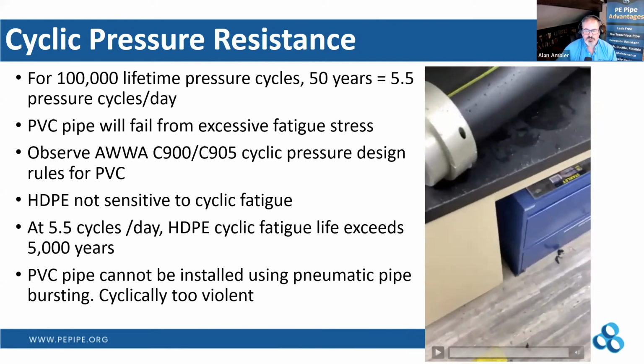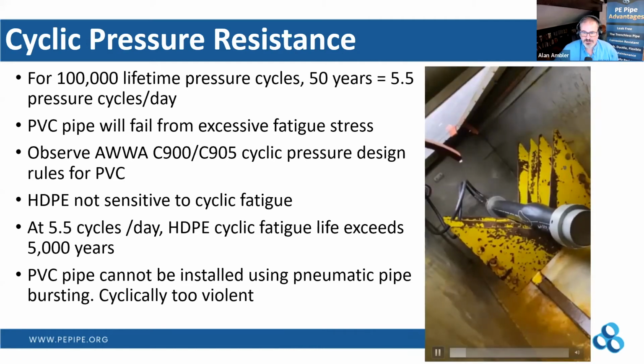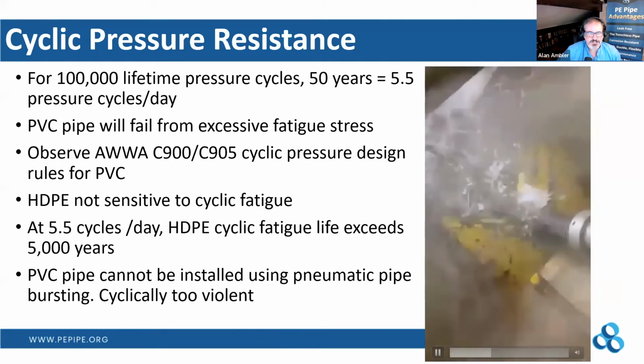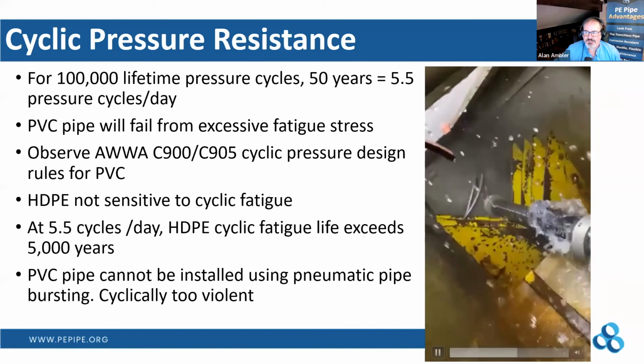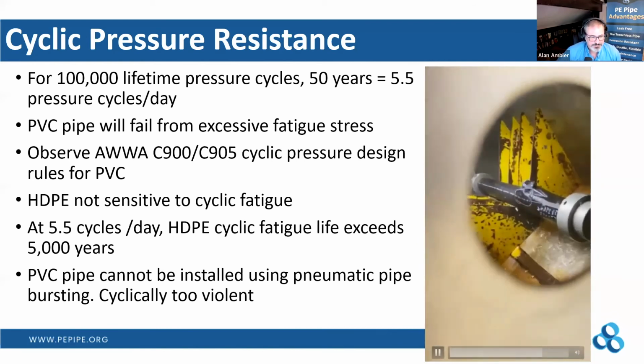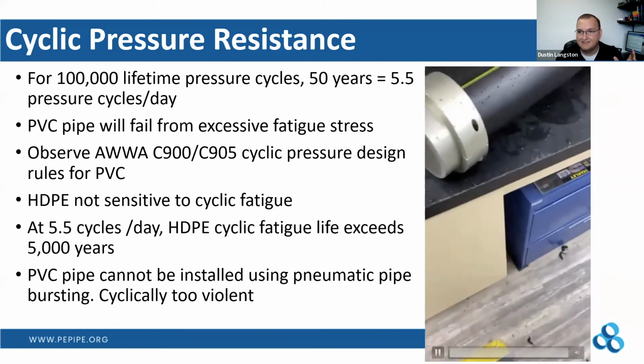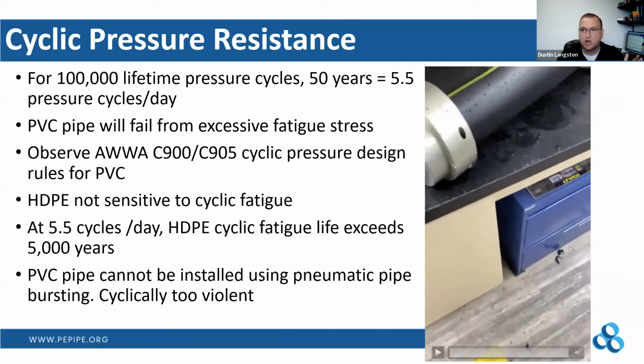Unfortunately, we didn't have any footage of the controlled chambers, but maybe Dusty, if you want to elaborate on the testing that would prove some of this cyclic pressure resistance that really backs up that claim that we've solved for fatigue. So HDPE pipe, with that low elastic modulus, the entire piping system acts like a giant shock absorber. Where you have, let's call it, 5 feet per second flow velocity through a pipeline, if that's in polyethylene and you have that flow stop, you're only going to see maybe 40, 50 PSI of a pressure spike, where in PVC you're going to see a couple hundred, and in ductile iron you're going to see 300 to 400. It's going to be a very violent, large pressure change.